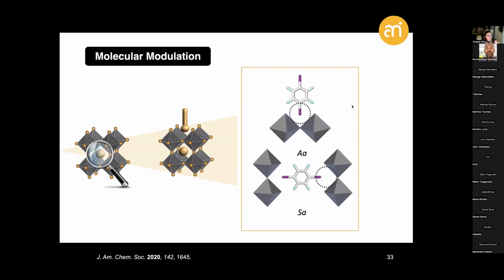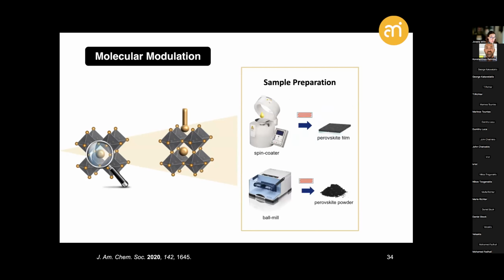Now, in order to really assess the presence of any of these modes of action in the resulting materials, they're commonly prepared by solution processing, so conventional spin coating from the precursor solutions followed by annealing to form the corresponding films, or, for higher quantities of material, especially for solid-state NMR spectroscopy, we also conventionally use mechanosynthesis, where the precursors are ground in a ball mill followed by annealing. In both cases, the modulator is included in substoichiometric amounts, commonly in the range of 5 to 10 mole%, that is then assessed in the resulting material.